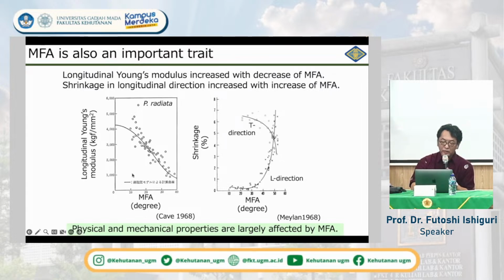For example, the MFA is related to the Young's modulus: wood with a lower value of MFA shows a higher value of Young's modulus. It is also closely related to the shrinkage value, the stability of the wood. If the microfibril angle is low, the shrinkage value is quite low. In compression wood, the microfibril angle is sometimes over 40 degrees, so the longitudinal shrinkage is very high in compression wood. So the microfibril angle is very important.